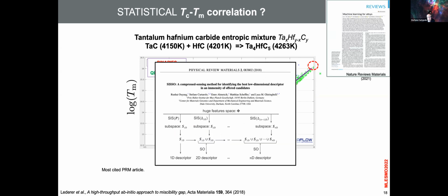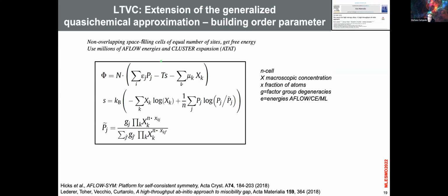Okay, so now let's look at how to make the miscibility gaps, and with this I will approach the end of the presentation. So you have the grand potentials here. You see that you have the probability of population times their energy. Remember that you change composition, so you need to remove the Gibbs part, so mu times the composition, and then you get an entropy. The entropy is an x log x plus the loss of entropy that you get when you go from above to below the line, from disorder to order transitions. Okay, this p tilde is a big calculation of the degenerations, because there is a trick here.